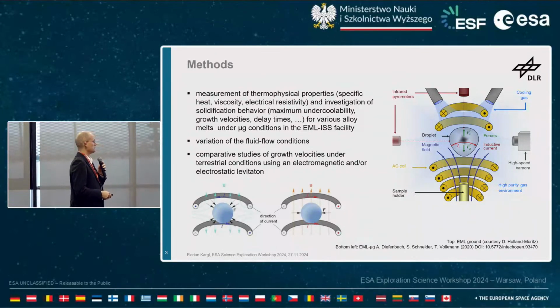And by heating the sample up, you have seen this melting and cooling cycle. Then if you apply this heating field to a certain extent during cooling, then you can also induce fluid flow in the sample at various levels. And this is also another opportunity that you have in microgravity to really vary the fluid flow conditions and then see what this has as an impact, for instance, on a solidification behavior.